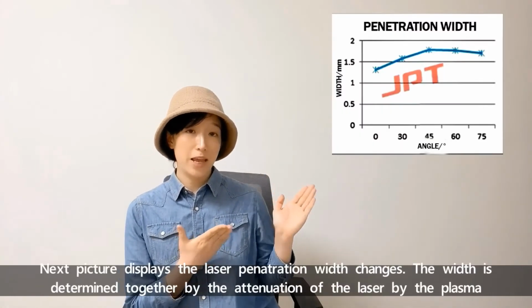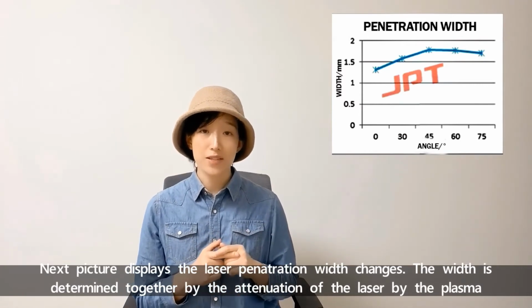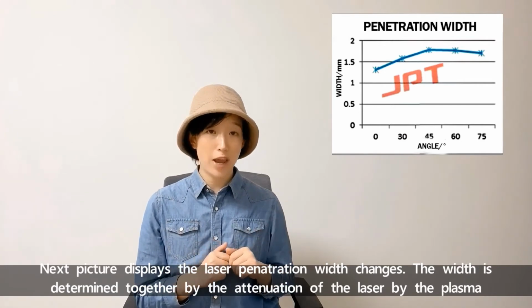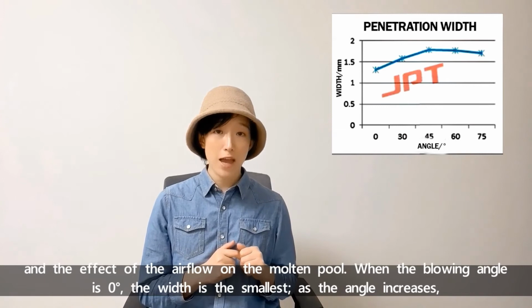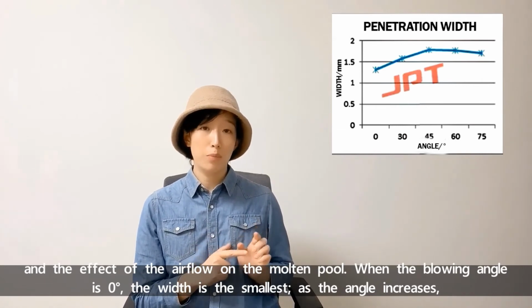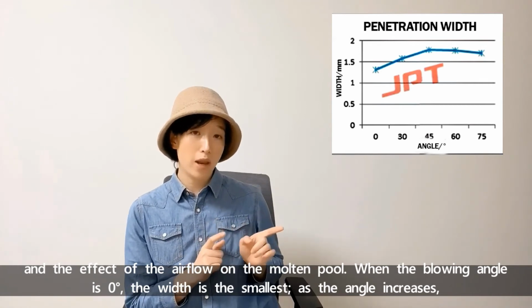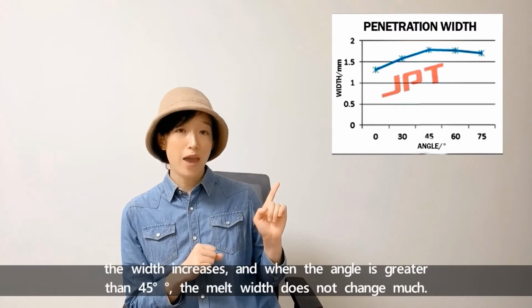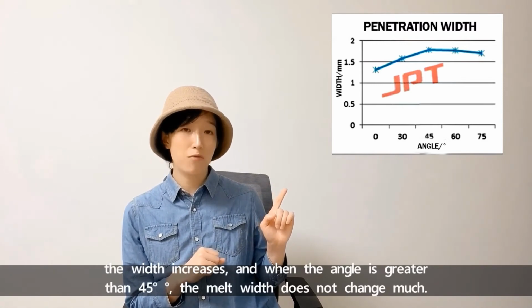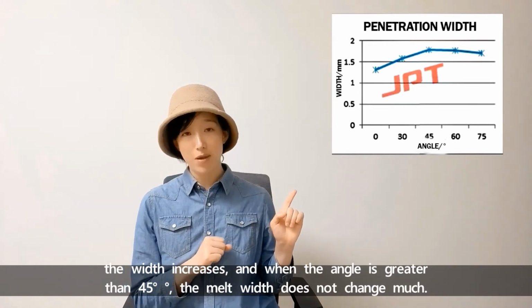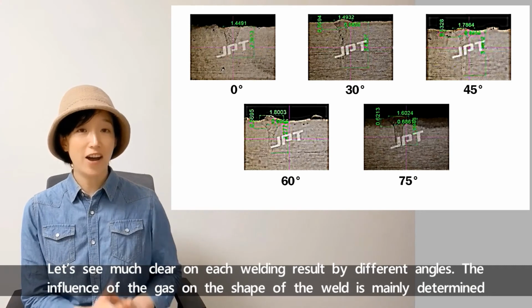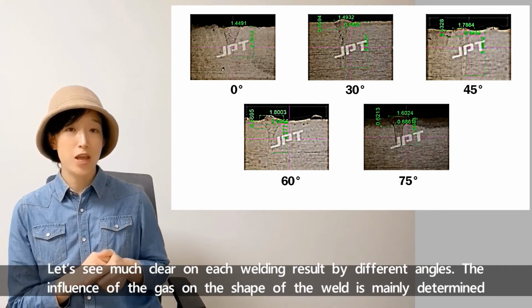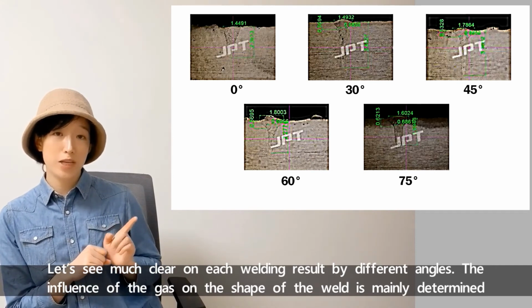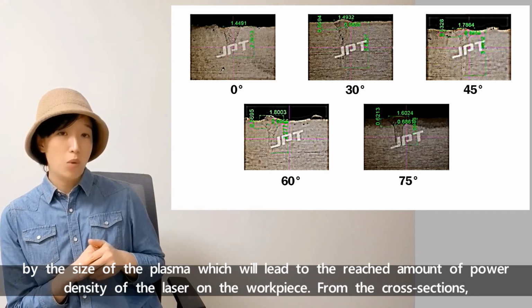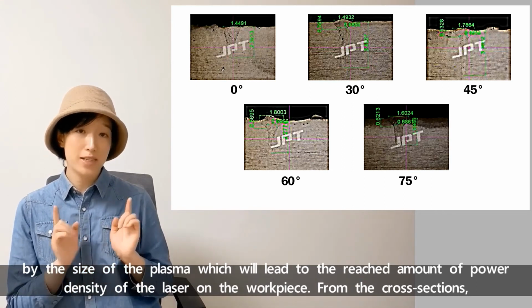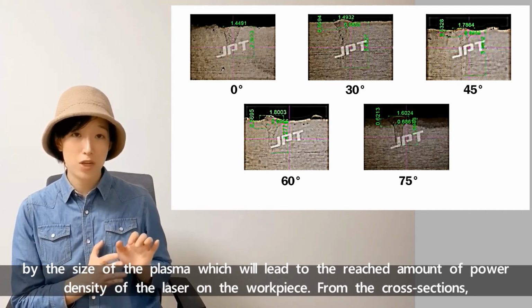The next picture displays how the laser penetration width changes. The width is determined together by the attenuation of the laser by the plasma and the effect of the airflow on the molten pool. When the blowing angle is 0, the width is the smallest. As the angle increases, the width increases. And when the angle is greater than 45, the melt width doesn't change much. Let's see each welding result at different angles more clearly. The influence of the gas on the shape of the weld is mainly determined by the size of the plasma, which will affect the power density of the laser reaching the surface of the workpiece.